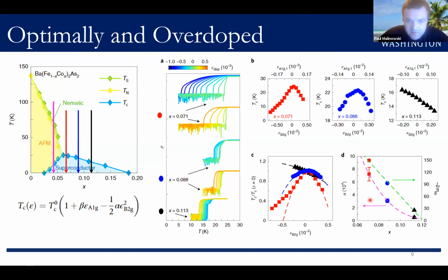And we can plot that as a function of doping. And what you see here is that alpha is quite large at optimal doping, approaching values of 100,000, and indeed shows a strong, striking compositional dependence.